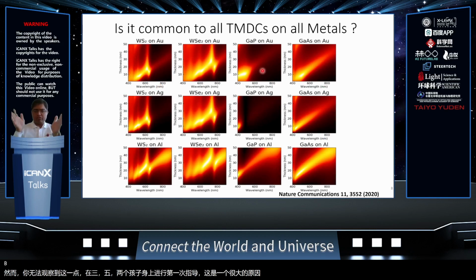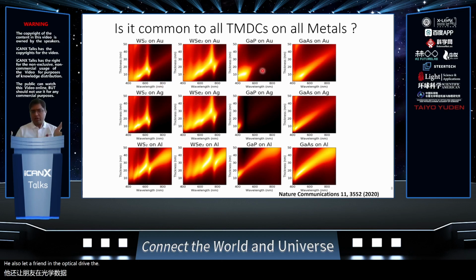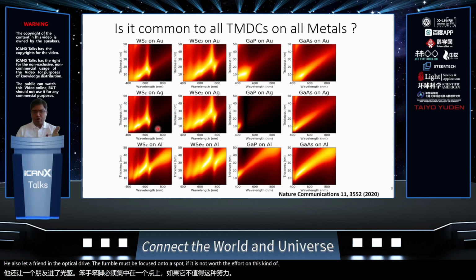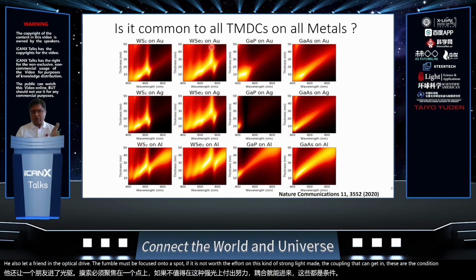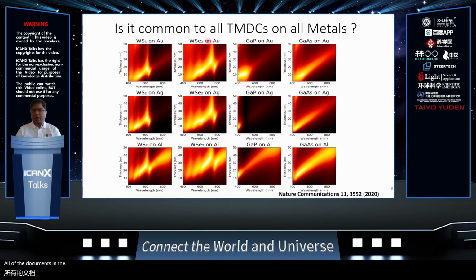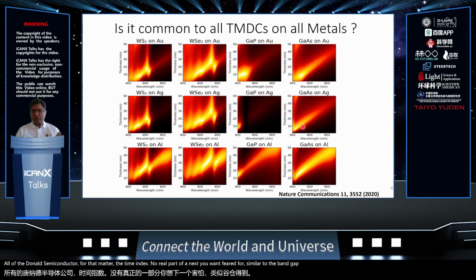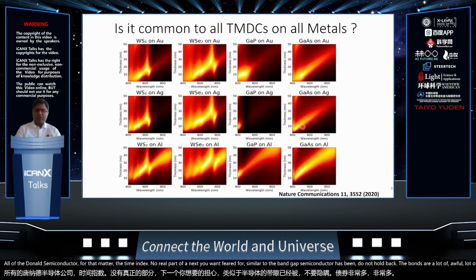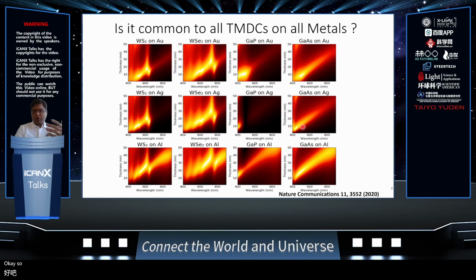The oscillator strength in the optical dielectric functions must be focused into the excitons. If it is not focused into the excitons, this kind of strong light-matter coupling that we get in these transition metal dichalcogenides, or all excitonic semiconductors for that matter, with high index or real part of index, you won't see it for similar band gap semiconductors which do not host excitons or do not have oscillator strength focused in excitons. Okay.